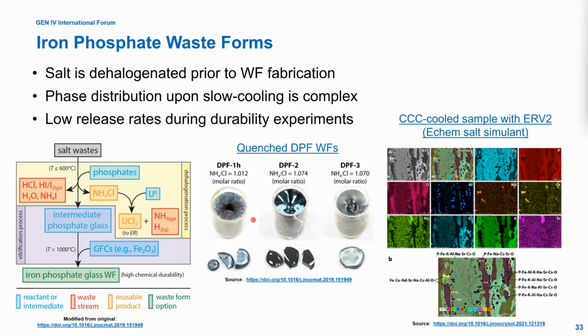This picture represents some examples of different materials we've made with different ammonium to chloride ratios and different salt loadings. You can see that some of these produce very crystalline products, whereas some of these are very amorphous. So we've tried to optimize the salt loading and the phosphorus to iron ratio to create the highest waste loading material we can that has the best chemical durability. This is something we've been working on for a few years, where we make these at PNNL, and then Bill Ebert at Argonne National Lab does the durability testing.